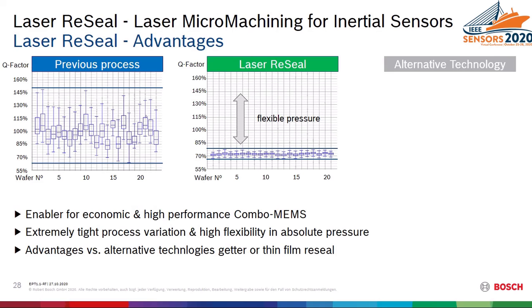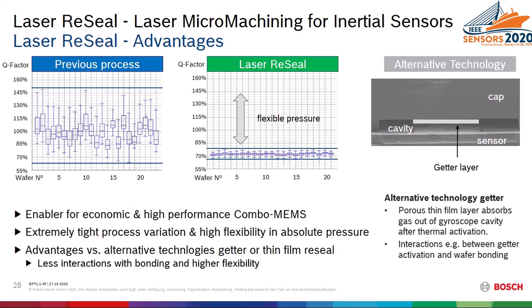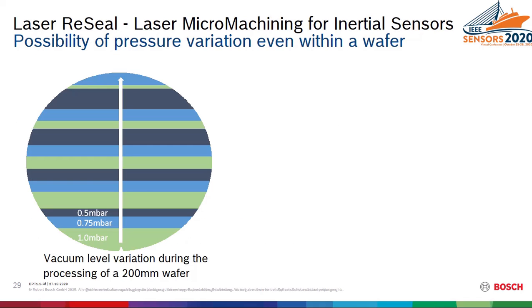Of course, there are other possibilities on the market to realize a one-chip solution. For example, you could use a so-called getter, which means you integrate a porous layer into the gyroscope cavity, which will absorb the gas and set you a low pressure. However, you need a lot of costly deposition and patterning equipment, and also you have some interference with the encapsulation process. And moreover, using getter technology, you could not realize a scenario like this.